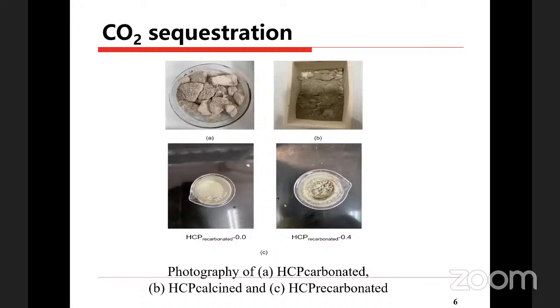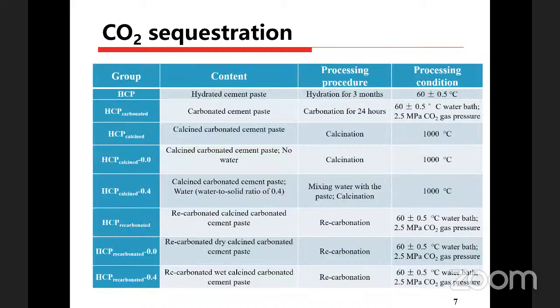And these are several photos. The first photo is about the carbonated hydrated concrete powders. Then we grind them, then we calcine them again, and finally we use the CO2 to recarbonate them again. And these are the exact groups, contents, processing procedures and processing conditions we used in this study.